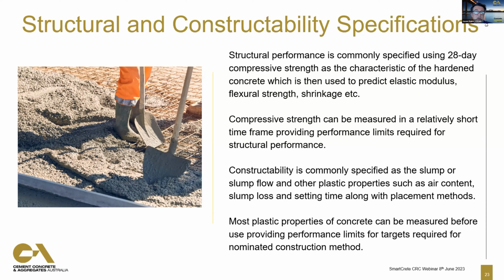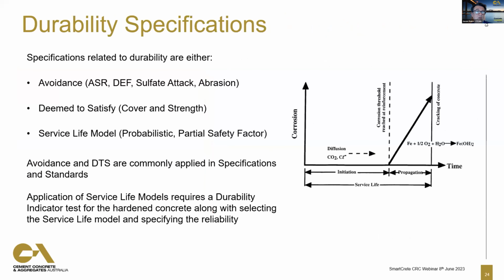Constructability is normally specified by a placement method and then an appropriate slump or slump flow. And again, on a performance basis, what we're looking for there is to make sure the concrete is compacted. So maybe we could have a compaction factor instead of that, not the compaction factor test, but a degree of compaction that's specified there instead of those other requirements. But really, the big opportunity is in durability. It is in durability that prescriptive specifications probably are more popular.